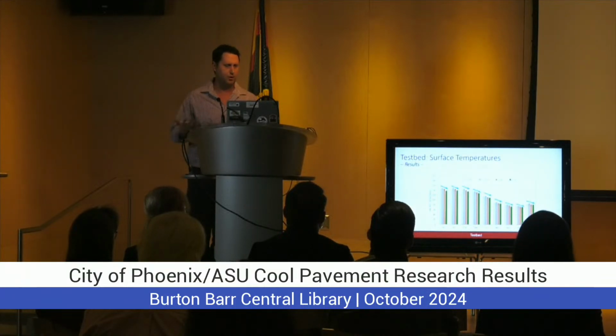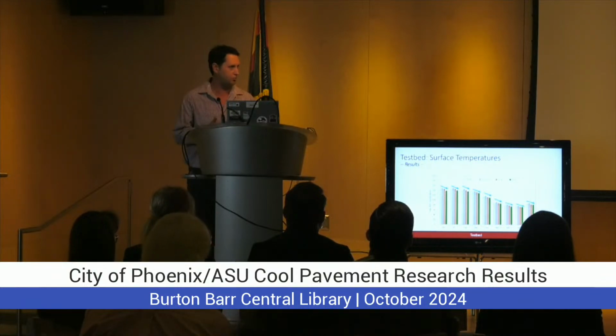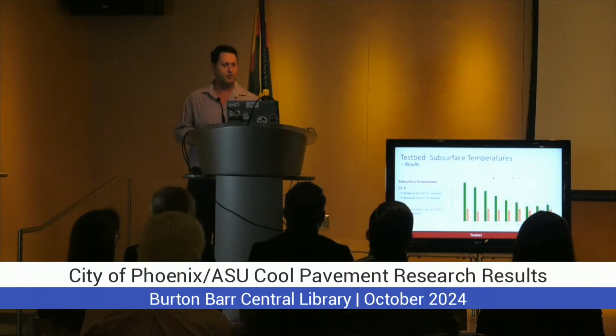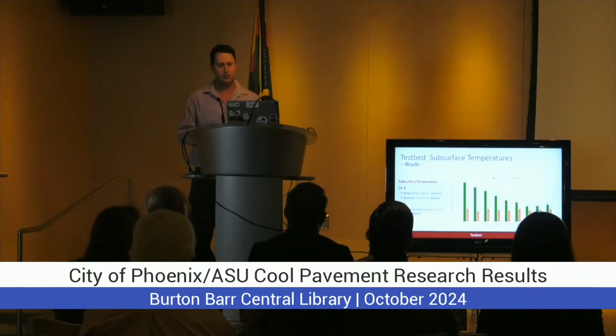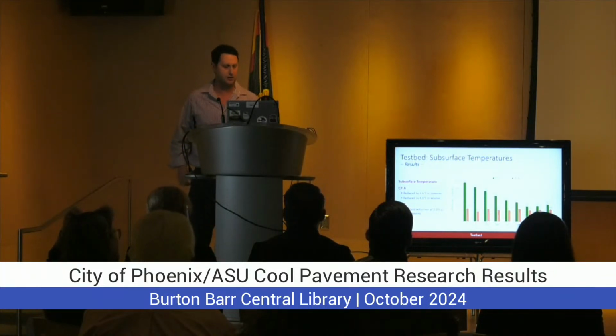What I want you to see from this plot, these are the average maximum temperatures from the top. And you see a decrease when we compare it to the control. If we zoom into this image, these are the average difference between the 2 products, product A and product B, compared to the conventional black seal that we use. For product A, early in the summer, the difference was up to almost 10 degrees. But then it reduced in the winter to 4. The other product remained constant pretty much all the time.